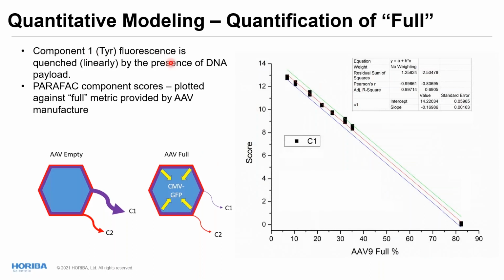And then with the samples that we had access to, we took our full samples and we titrated them down with empties. So we have essentially mostly full and then mixed in empties until we got down to mostly empty. We can see here with basically the PARAFAC score of component 1, which is that tyrosine-like component, we see this quenching as we're adding more payload to the AAV capsid with a quite nice R squared of 0.997 here. So really interesting quantification of the bound or interacting DNA in the AAV capsids.